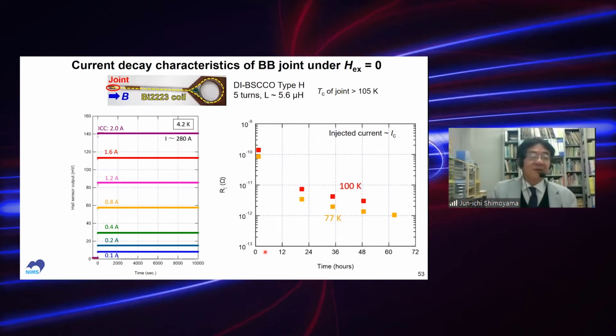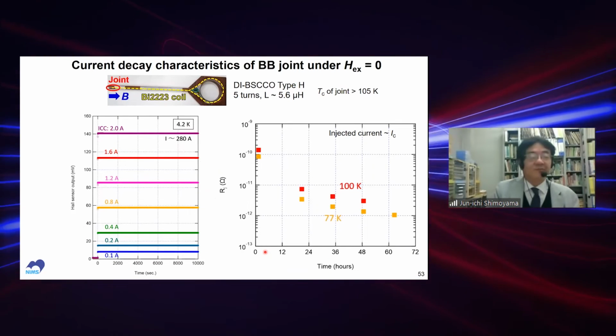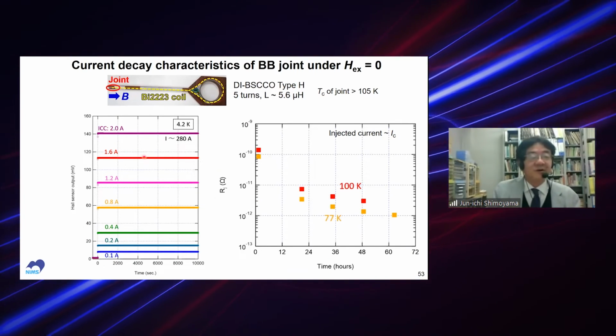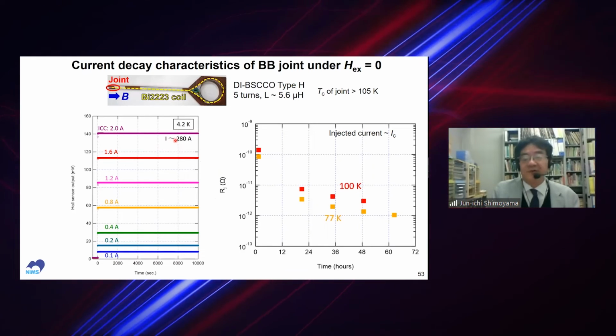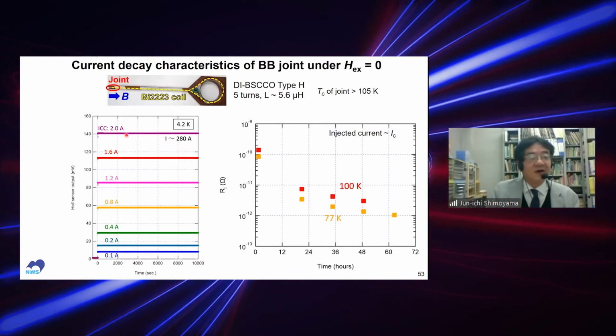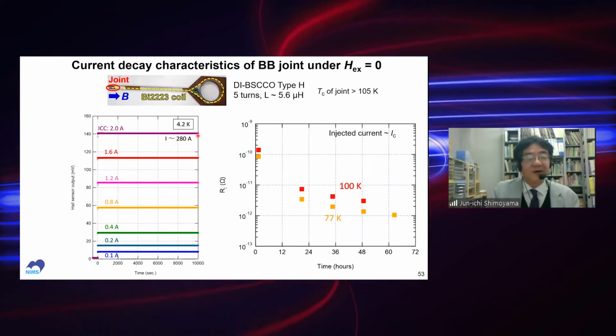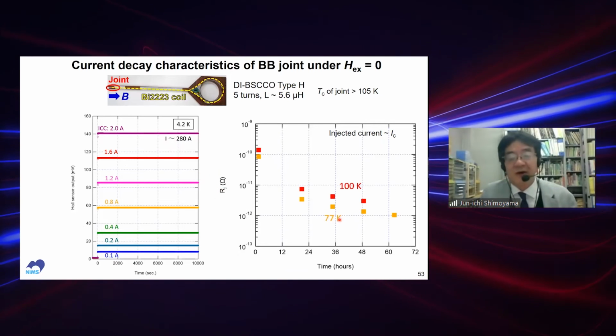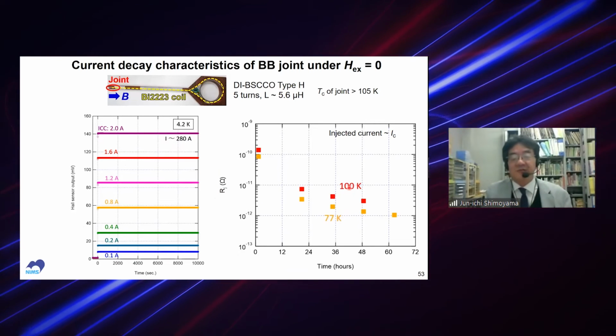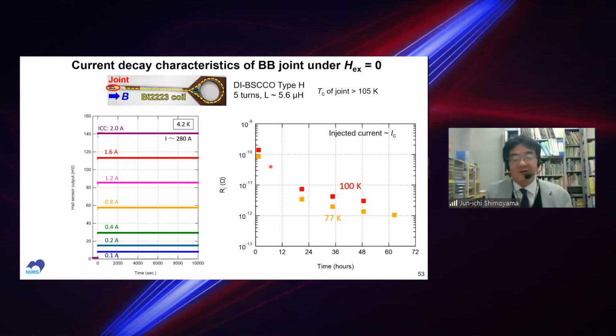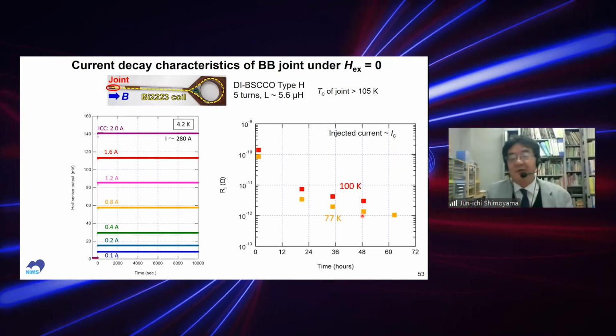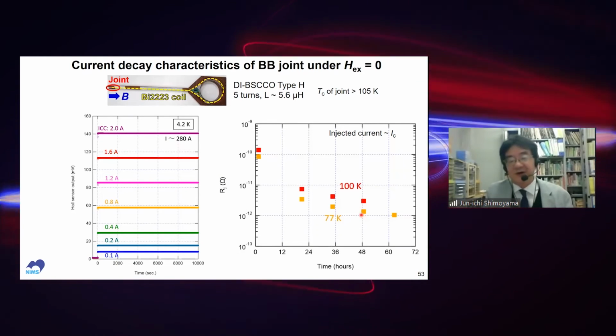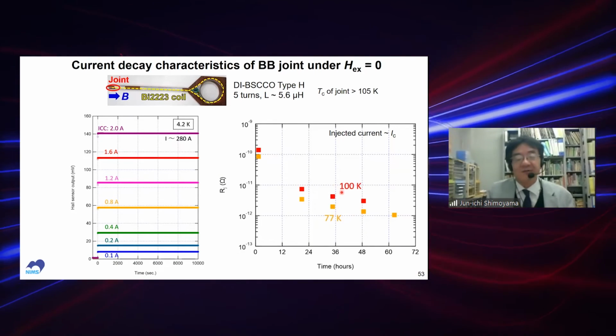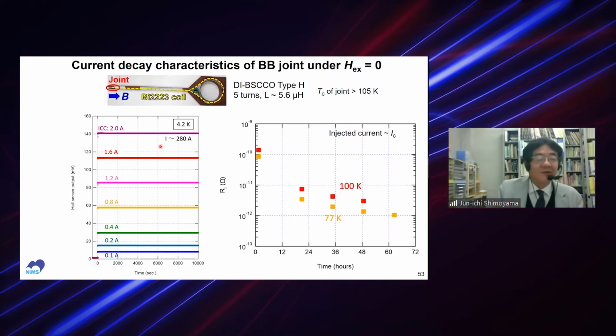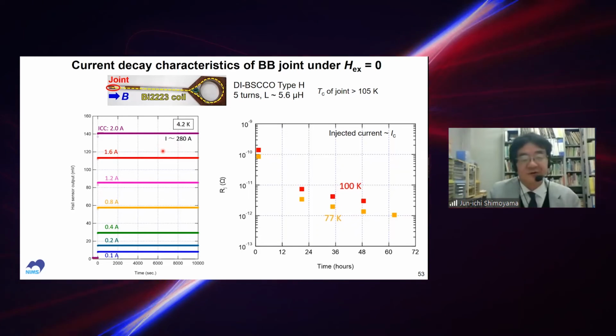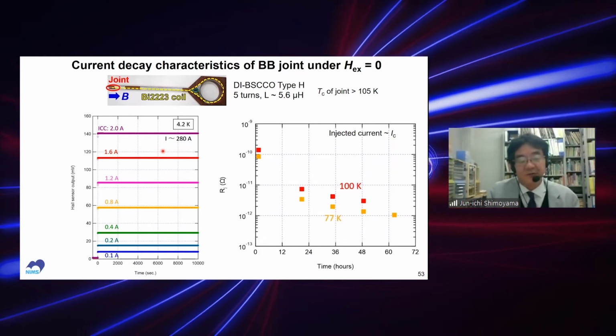So current decay measurements were also performed for this joint, and we confirmed that at 4 Kelvin the current decay rate is very small, while at 77 Kelvin and 100 Kelvin the current decay ratio is relatively large. However, we can observe the persistent current even at 100 Kelvin for this joint, because the joint Tc is 105 Kelvin.